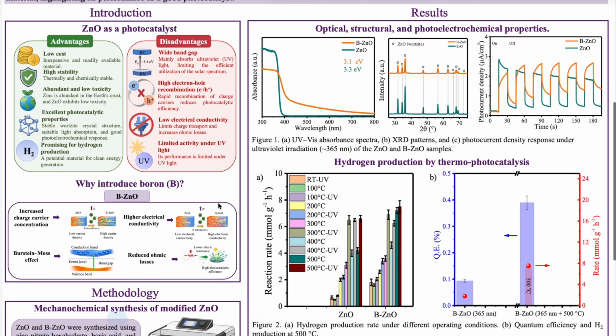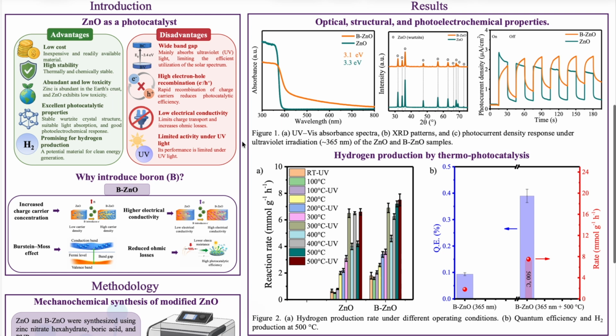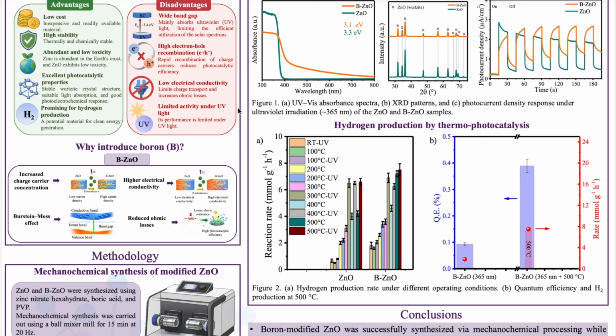However, ZnO also presents several important limitations. Its relatively wide band gap of approximately 3.4 electron volts means that it mainly absorbs ultraviolet light, which represents only a small fraction of the solar spectrum. Moreover, rapid recombination of photogenerated electron hole pairs significantly reduces its photocatalytic efficiency. Its relatively low electrical conductivity also limits charge transport and increases ohmic losses. As a consequence, the photocatalytic activity of pure ZnO remains limited.